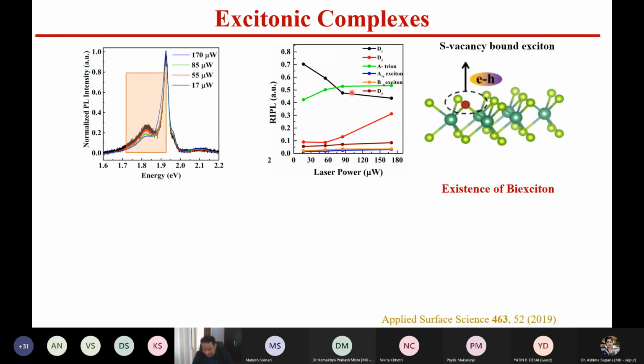If you have some defects in the sample, these defects will saturate first, before the other optical transitions. Here, this is the relative integrated PL intensity. You see a black curve going down, while the rest of the curves go up. Now if you have excitons bound to defects, these are very minor defects in the sample, and those excitons bound to the defects give rise to these optical transitions.